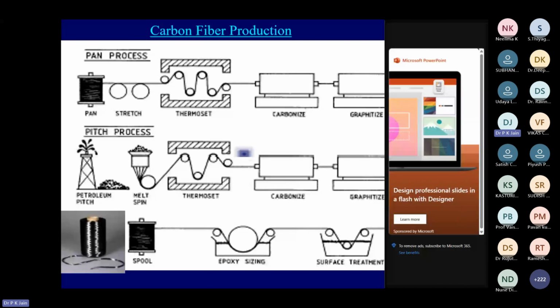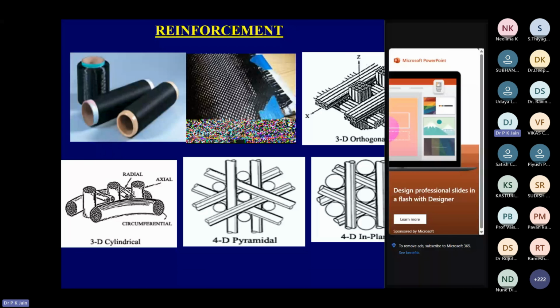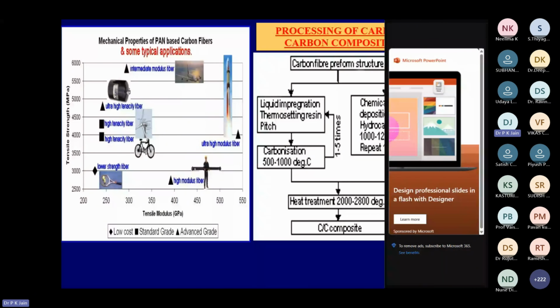Carbon fiber can be unidirectional, bidirectional, tridirectional, radial, or any multidirectional form. Depending on your application, one can use carbon fiber to get the best mechanical strength. Aerospace requires a very high modulus fiber, whereas a cycle, a windmill, or a tennis racket requires a low modulus but high strength fiber. The cost is very different. Low modulus or high strength fiber costs around 4,000 to 5,000 rupees a kilogram, whereas high modulus fiber comes to around 25,000 to 30,000 rupees a kilogram.